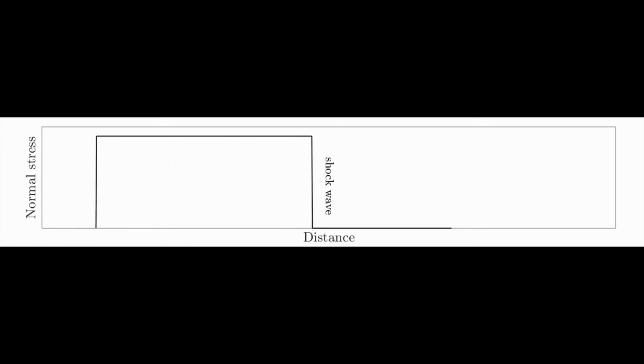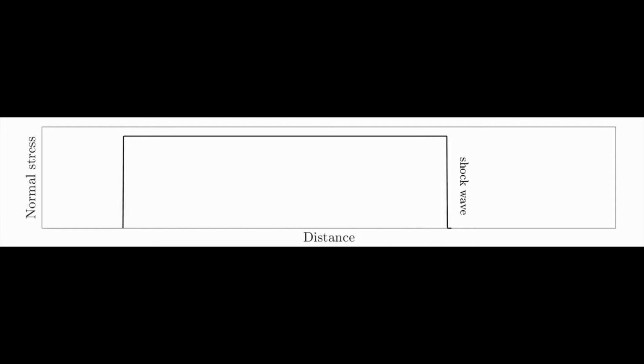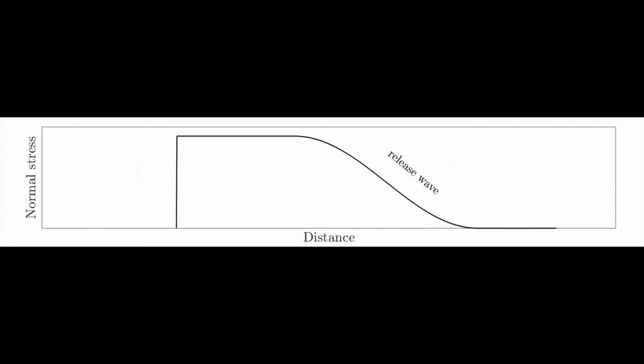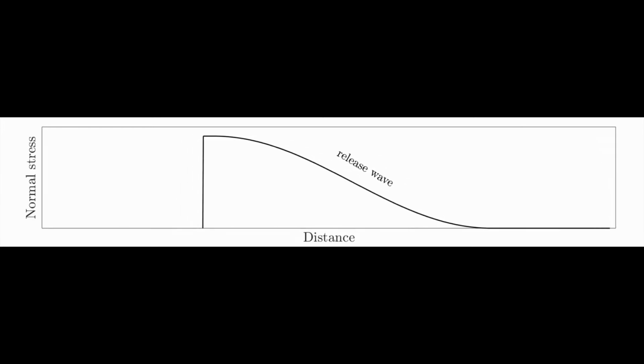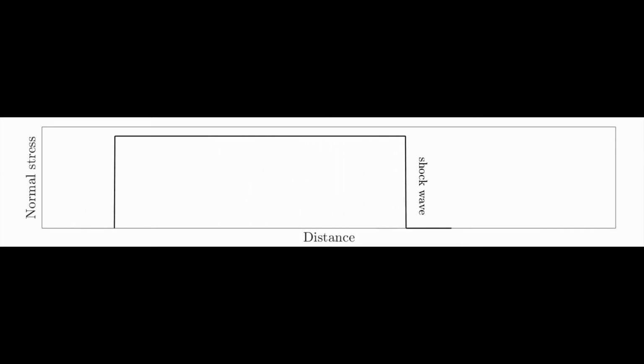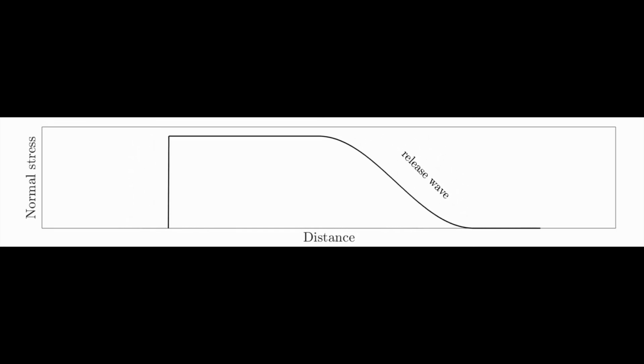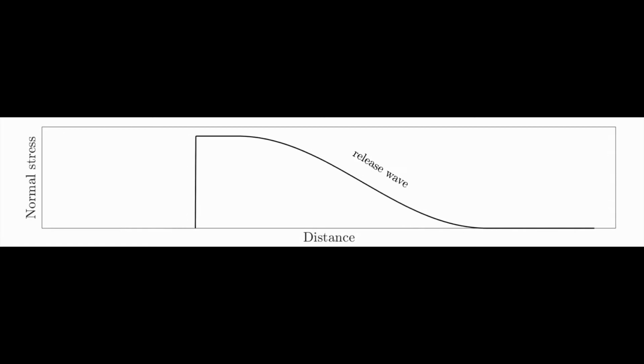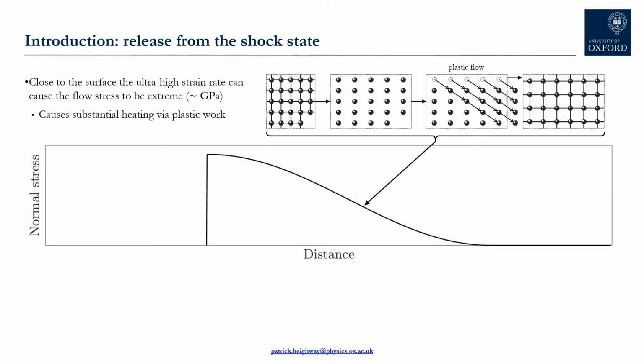Now, the canonical treatment of shock release treats the process as being isentropic, so that means when the crystal expands back to ambient volume, its temperature evolution is governed exclusively by the thermoelastic effect, which causes the crystal to cool by typically several hundred degrees during release, at a rate dictated by the Grüneisen parameter. However, that premise, that release is isentropic, is predicated on the notion that the typical strength or flow stress of the material during release, which determines the rate at which plastic work is performed, is negligible compared to the overall pressure scale at which the release is taking place.